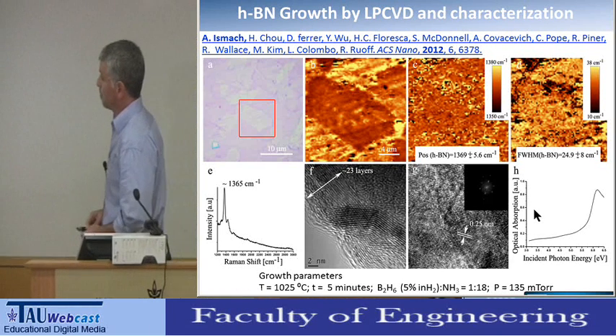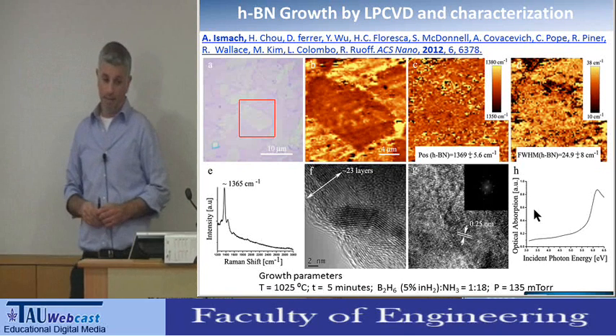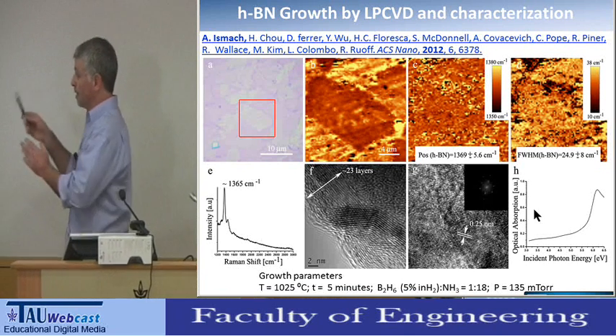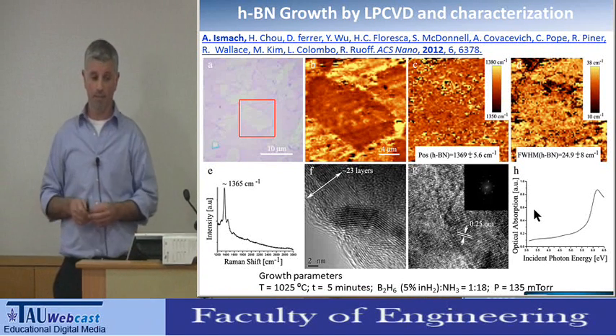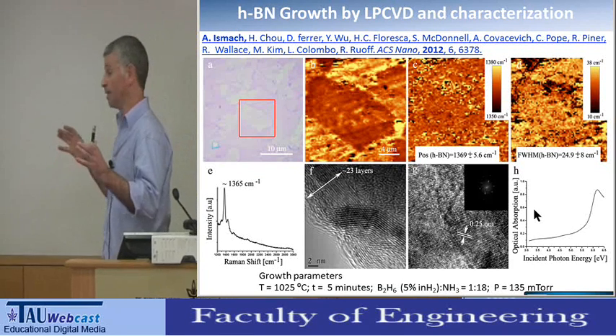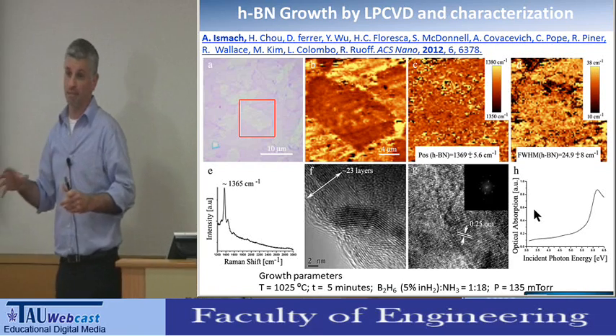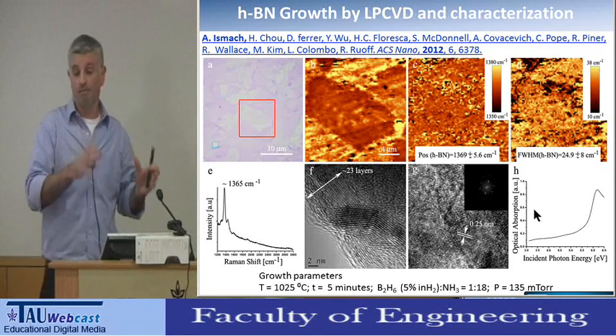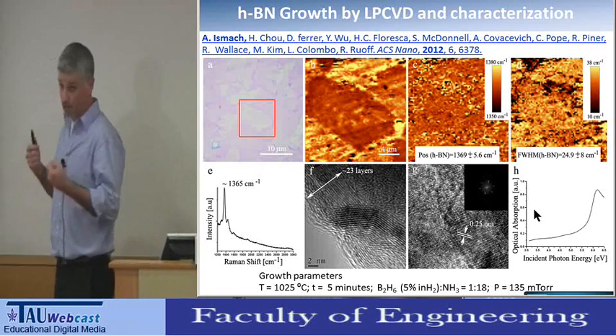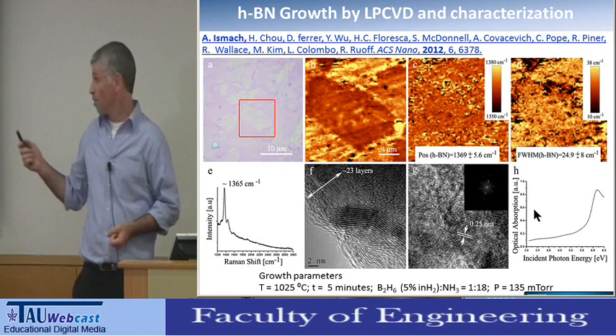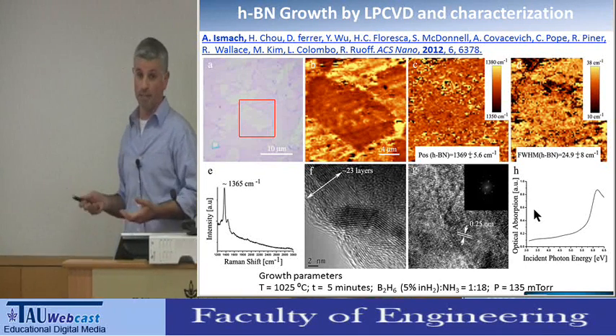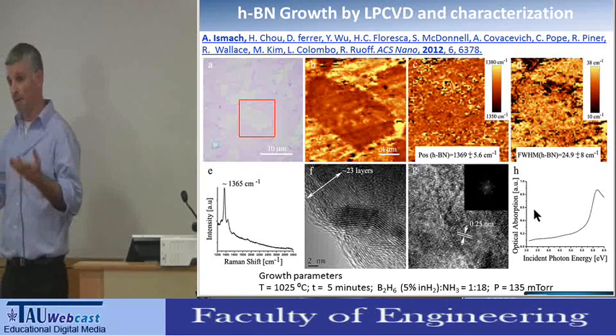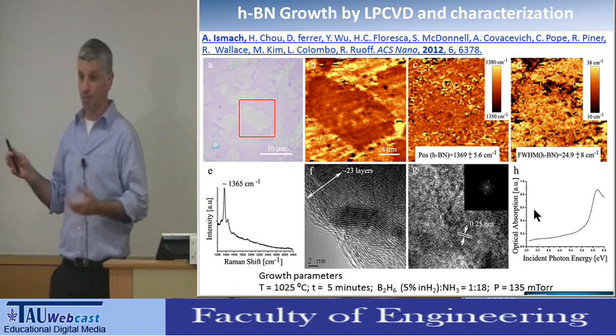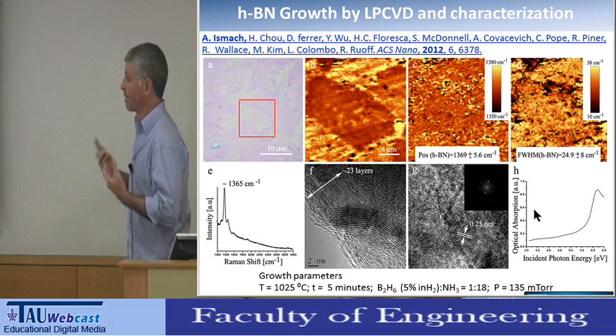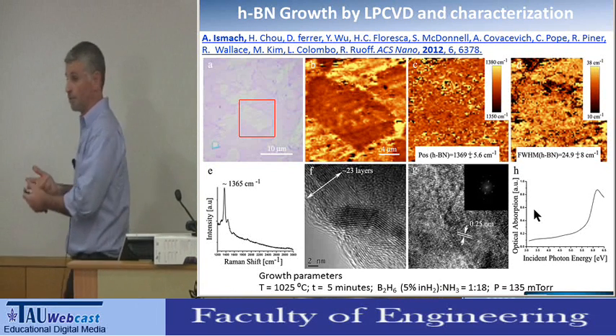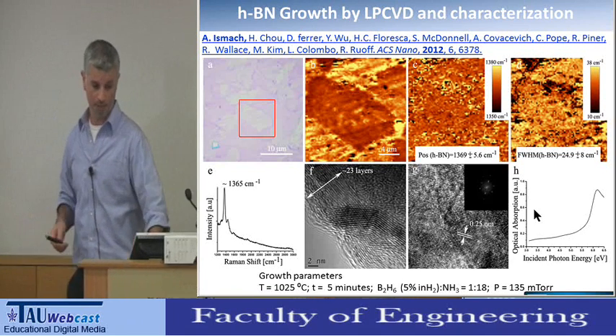And one of the problems with this material is that there is no way, actually there is a way, and I will show you in a minute, but till now nobody showed a way to characterize in two dimensions the number of layers and the quality of these materials as we have tools for graphene. Raman characterization, again, for graphene is very useful for that, but not for hexagonal boron nitride. In hexagonal boron nitride, we have only one peak, and there is not much to do with it. In graphitic phase, by comparing between the intensities, the ratios, the position of the different graphitic peaks, you can get a lot of information about number of layers, quality, doping, strain, etc., but not in hexagonal boron nitride.